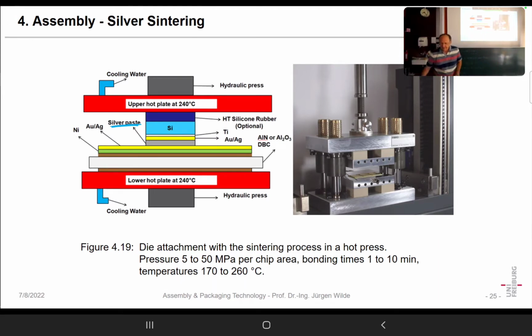the pressure. What is important here, you see these holes. In these holes, there are some heater elements. So we have a quite uniform heating. And what is really important is that the plates coming together are really parallel. That's really important, because otherwise a point-wise contact will crush the chip. Okay, that's a sinter press. As long as it is parallel and as long as the temperature is well controlled, it is uncritical.